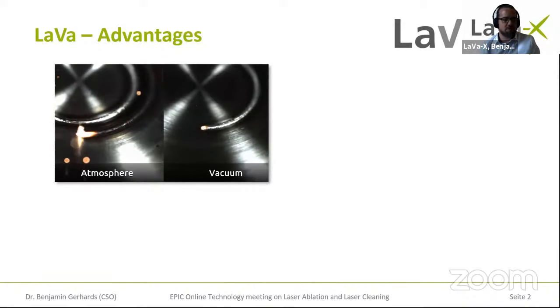And on the right side, with the same parameters, you can see that we have a significantly smaller molten pool. We have no vapor plume above the capillary, and spatters that occur are quite tiny, so they do not adhere to the surface. And all of this is due to the reduction of the evaporation temperature of materials such as steel, iron, aluminum, and copper.